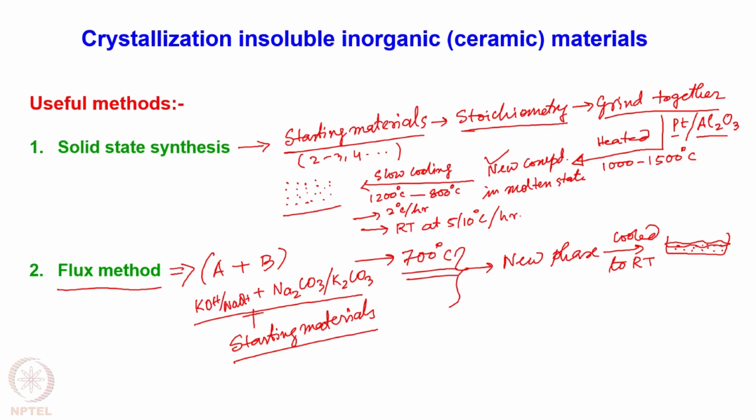Mind you, the crystals that have formed are now insoluble in water, whereas the solidified flux is still soluble in water. So the flux in the reaction mixture can be washed out, and the tiny crystalline particles that have grown from your starting materials, which formed a new crystal, new compound, new phase, can be isolated from this mixture.